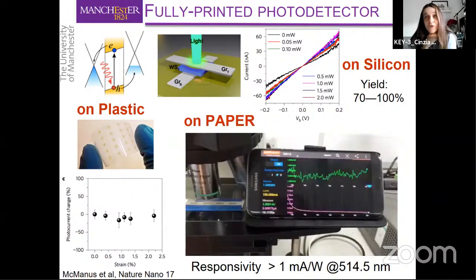And with the inkjet printer, it is obviously very easy to print many devices in one go. And actually, this is a requirement in inkjet printing. The yield is very important. And so because of that, we started to print arrays of heterostructures. So basically, something that looks like this. And in this picture here, I hope you can see there are some black lines, horizontal and vertical. So these are the top and bottom graphene electrodes. And then in the middle of each junction, there is this yellowish, greenish square, which basically corresponds to the printed tungsten disulfide film. So in the case of silicon, we printed 10 by 10 arrays.